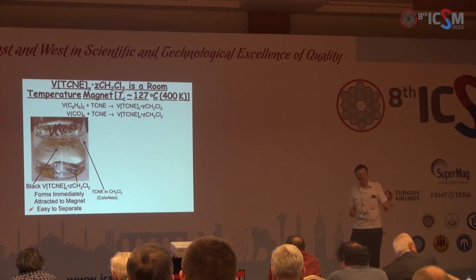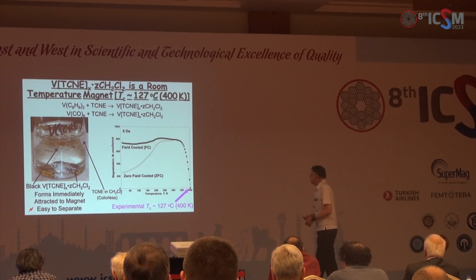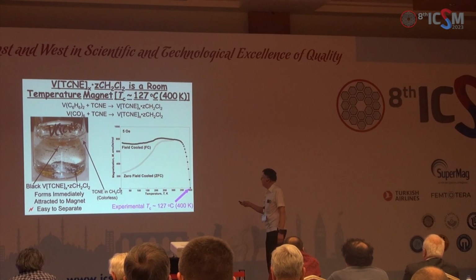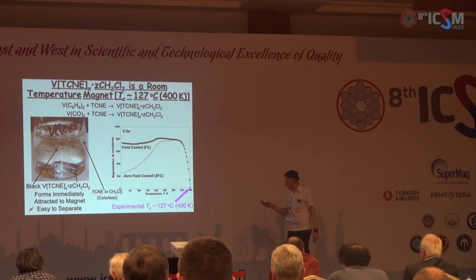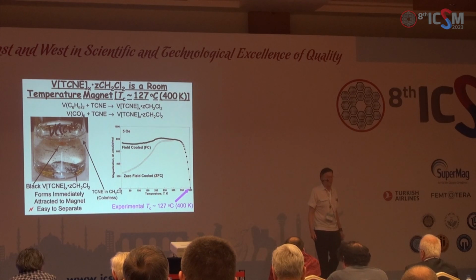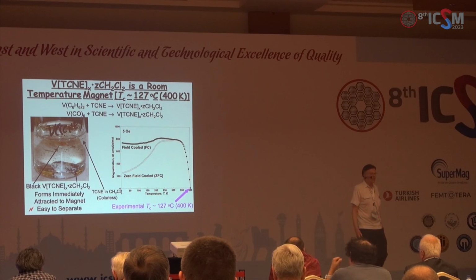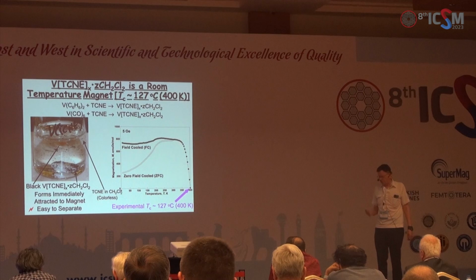If you measure the magnetization versus temperature at low field, you can see there's a bifurcation between the field-cooled and zero-field-cooled curves, and it goes to zero at 400 Kelvin. So the experimental ordering temperature is 127 degrees centigrade, 400 Kelvin.